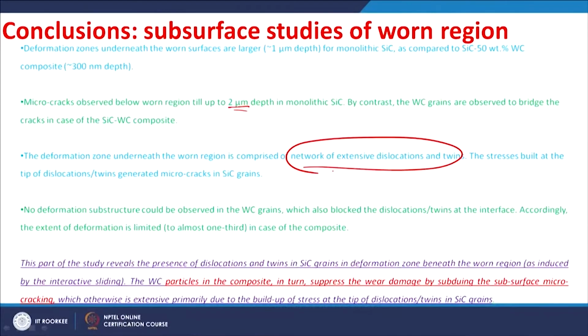The deformation zone underneath the worn region comprises a network of extensive dislocations and twins. So, the stresses built up at the tips of these dislocations or twins generate the micro cracks. So, you see a lot of micro cracks in silicon carbide grains, whereas no deformation substructure is observed in the tungsten carbide grains, which also block the dislocations or twins at the interface. Therefore, the extent of deformation is limited to almost 1/3 of what we observed here in the case of the composite.